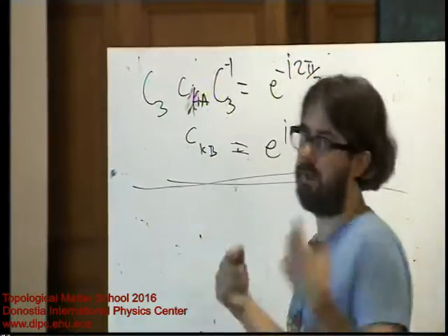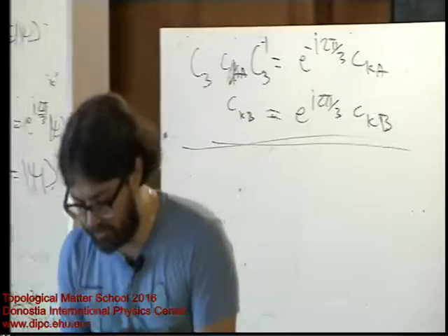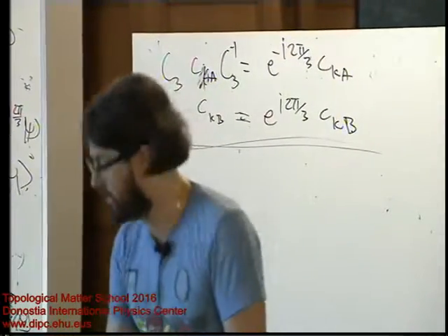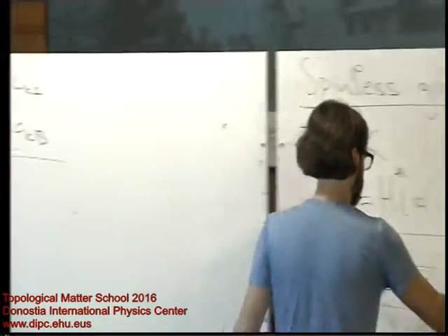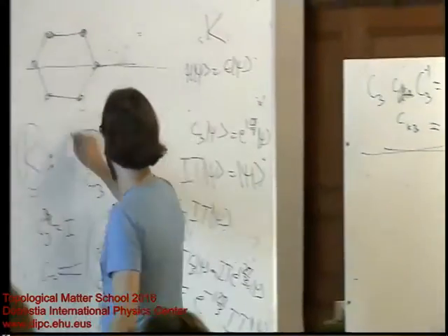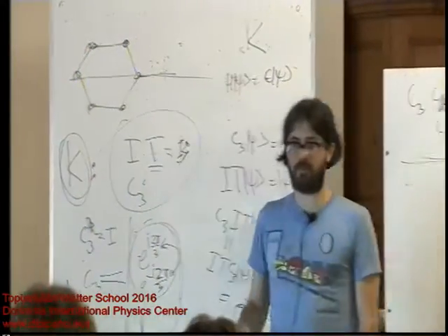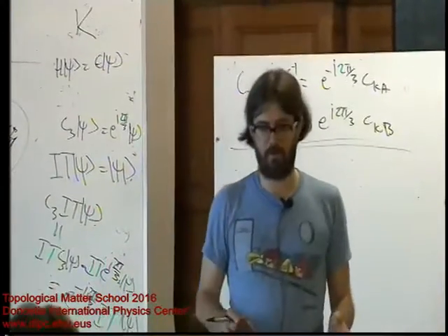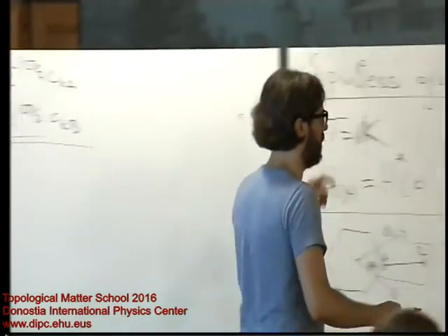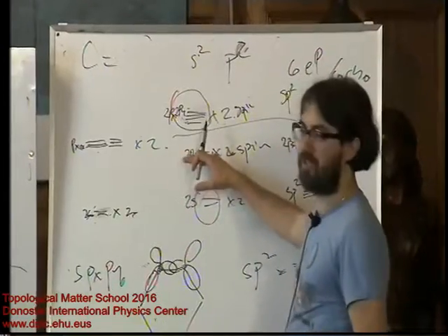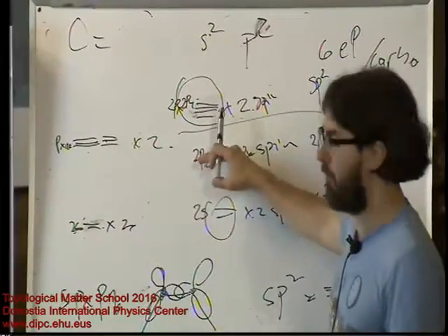But as I look down on them from this side, they look like s orbitals. So without any tight binding Hamiltonian or any low energy model, graphene has Dirac points stuck at the corner of the Brillouin zone, stabilized by C3 and inversion and time reversal. In general, out of the pz orbitals, which we've established are the ones relevant to the Fermi level.